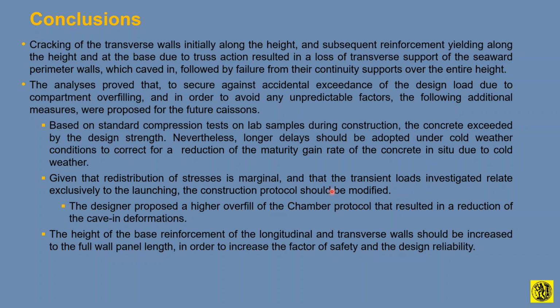And also, just to make sure, the bottom reinforcement in the maximum bending region was actually continued over one full panel width plus one development length, horizontally and vertically, with additional stirrups in there, in order to make sure that the bottom part of the caisson in the lower 5-6 meters was well reinforced in case a 45-degree diagonal crack would like to form by any means, in order to keep the deformations and the stresses as they should be after the cracking.